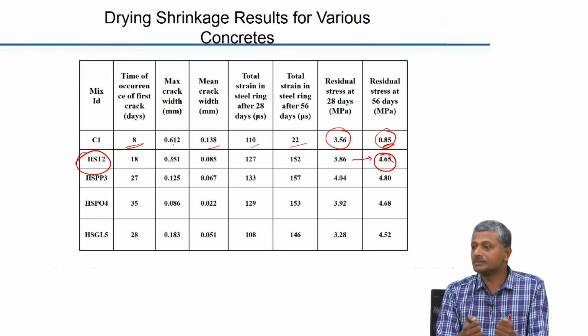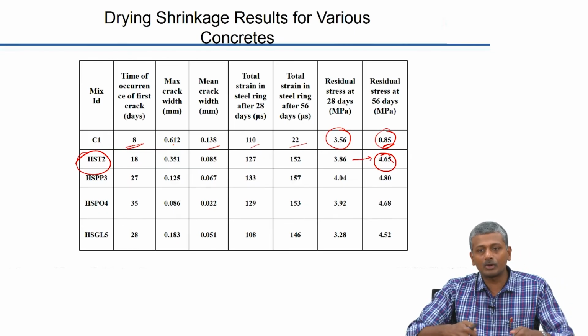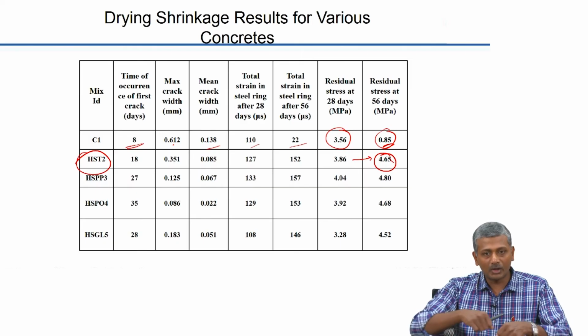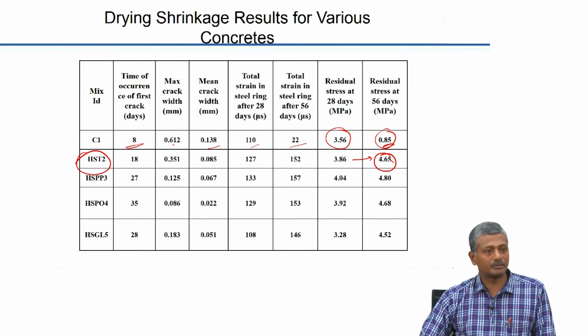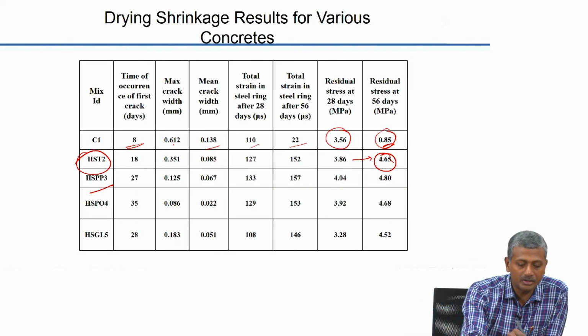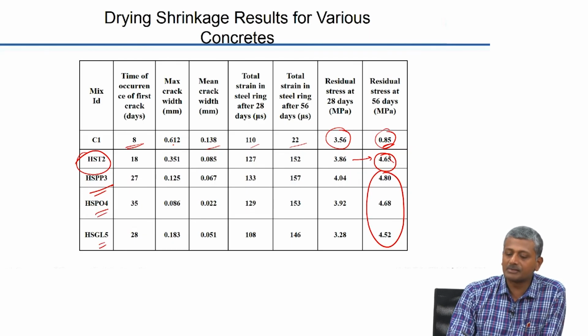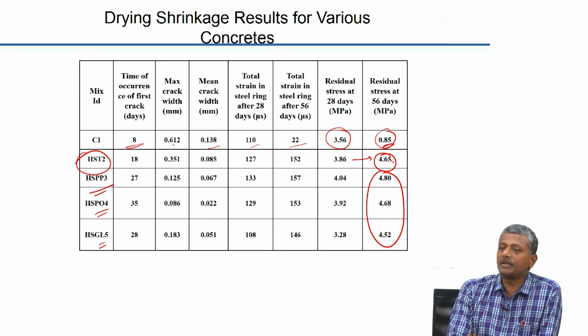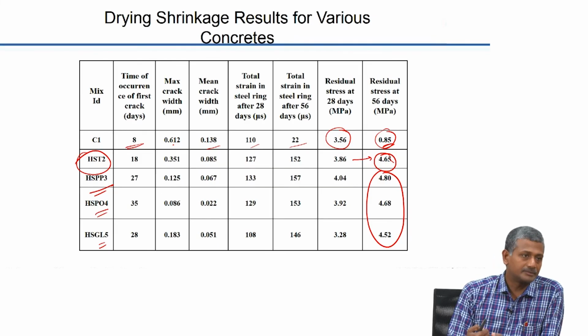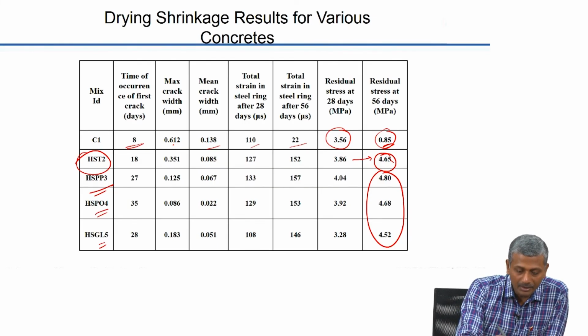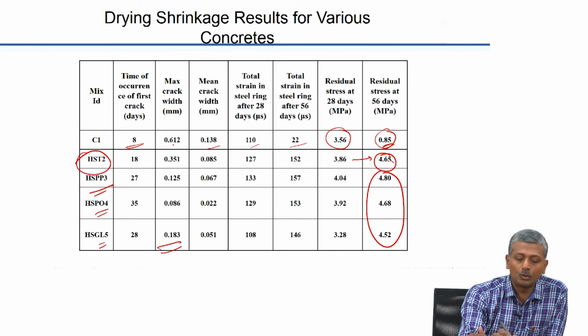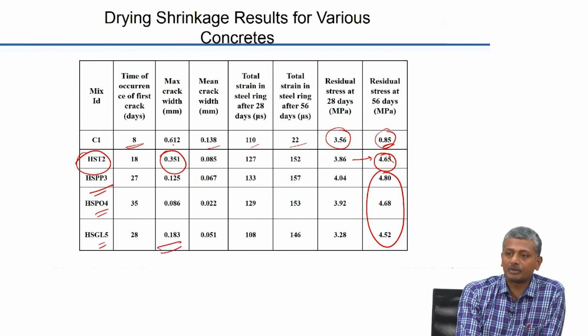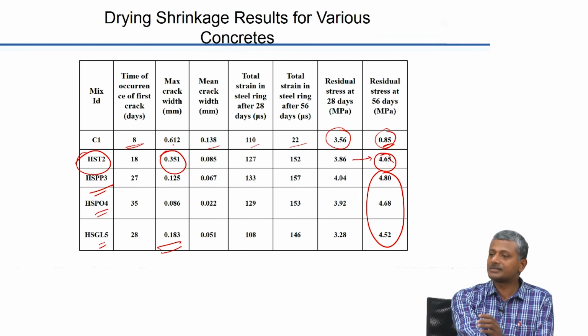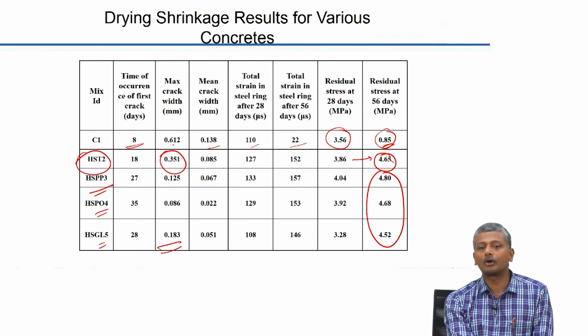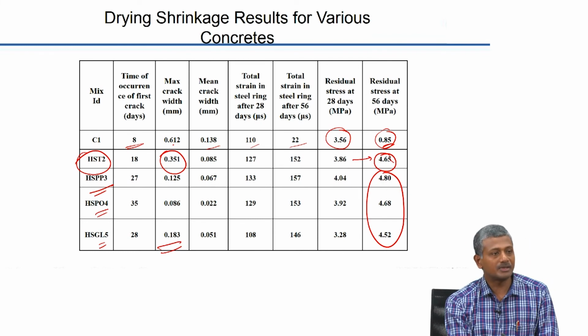That means the shrinkage of the concrete keeps on building up the stress which is going on being taken by the steel fiber concrete. And similarly, when you have the combination of steel, polypropylene, polyester, glass, you have high levels of residual stress which are still being taken because the fibers are still bridging the crack. Okay. But interestingly, the crack widths are significantly lower as compared to even the steel fiber concrete.